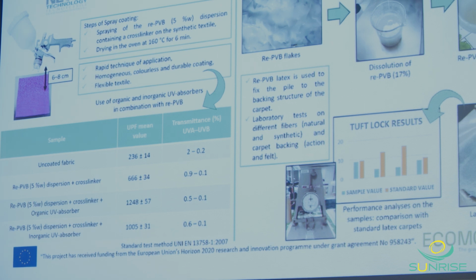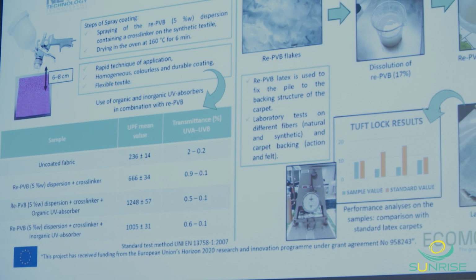The other applications are related to coatings in the textile sector. Here there have been 2 applications, one for coatings based on recycled PVB for UVA protection. Here the Next Technology Textile Center in Italy has been working on this application, and they have found good results in the use of PVB. Even without the UVA absorber, it could protect from ultraviolet radiation, but increasing this with inorganic or organic ultraviolet absorber, the results have been good. And in the case of the carpets, the results have not been so good, but this could be related to the format preparation. Here we have been working with solutions of recycled PVB. So the results in terms of adhesion have not been good. And we think that probably working with dispersion, this could be better.